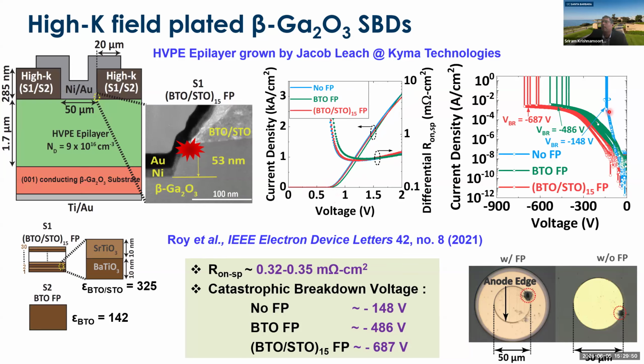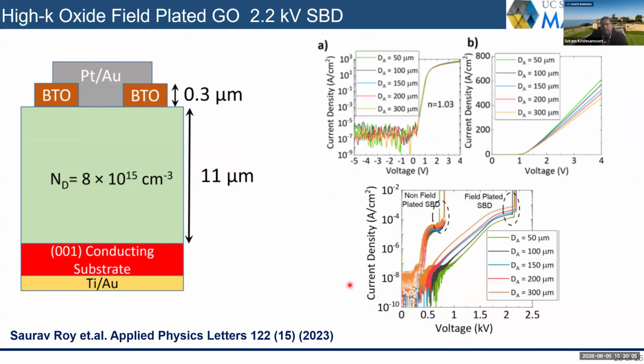But we got a huge improvement in the reverse blocking capability, which is exactly what we want. And so we were able to get on-resistance below 1 milliohm centimeter square at 600 volts using this approach. Later, we extended this idea by using low-doped thicker epitaxial layers, 11 microns of epitaxial layer